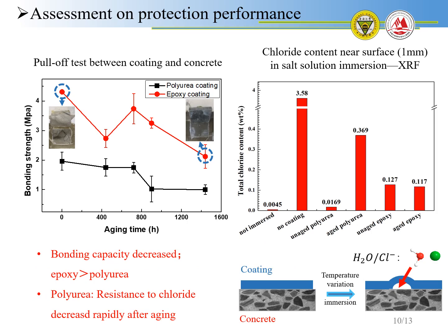Although from the structure evaluation we can find the weatherability of polyurea is better, things are different when assessing the protective performance. The reason is the poor bonding property of polyurea. Look at the left figure. The bonding strength is reducing with aging time, and the failure mode of epoxy resin changed from concrete matrix fracture to interface debonding. But the failure mode of polyurea is always debonding at the interface, because the bonding strength stays at a low level. Due to this performance, polyurea does not show as good protection as its weatherability.